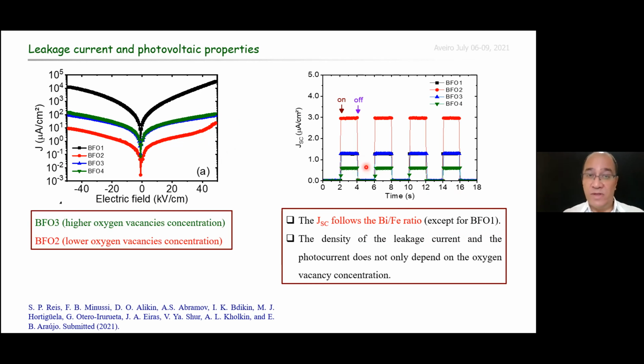BFO1 is not the lowest, as we can see in this figure, it suggests that the leakage current and the photocurrent do not only depend on the oxygen vacancy concentrations. Probably competition between different defects is responsible for these physical properties in BiFeO3 thin films. So our suggestion is that these properties must be investigated in detail in the next studies.